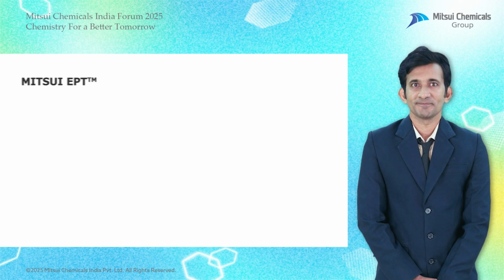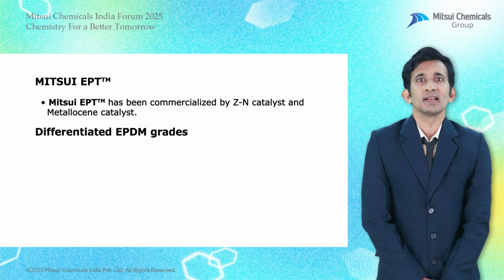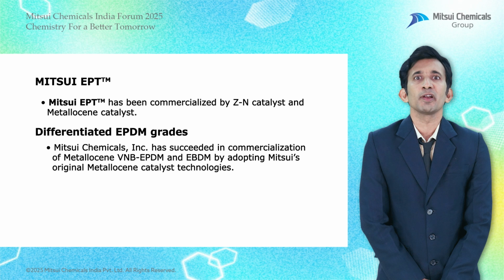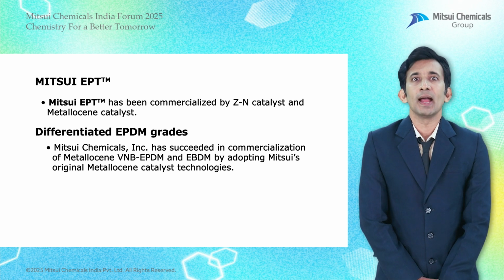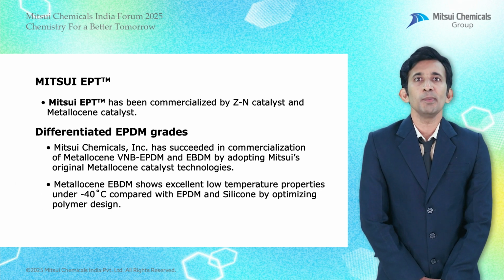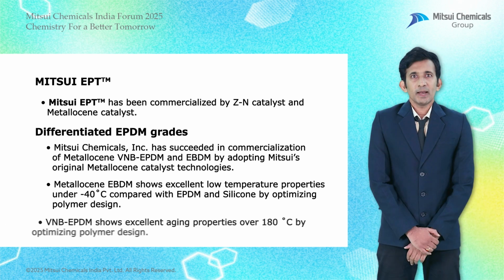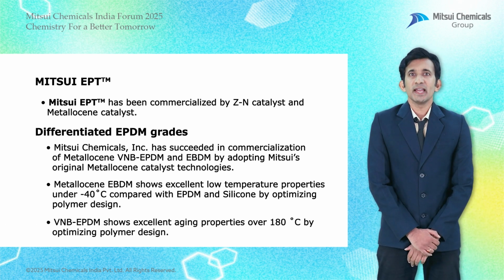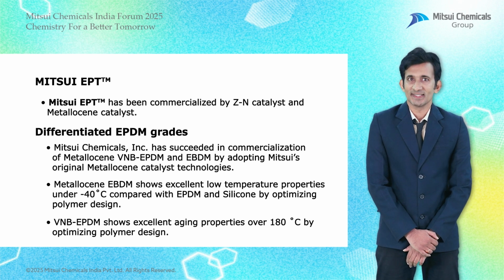To summarize, Mitsui Chemicals Inc. has succeeded in commercialization of metallocene VNB EPDM and EBDM by adopting Mitsui's original metallocene catalyst technologies. Metallocene EBDM shows excellent low temperature properties under -40 degrees Celsius compared with EPDM and silicone by optimizing polymer design. VNB EPDM shows excellent aging properties over 180 degrees Celsius by optimizing polymer design.